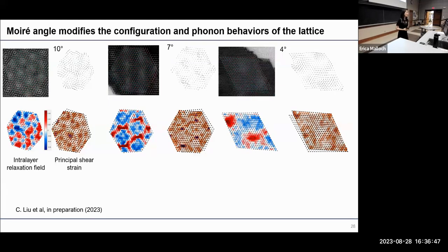We can actually map out the intralayer relaxation field together with the principal shear strain. Those features all arise because each layer is no longer a perfectly hexagonal lattice. Instead, they will be distorted in the presence of the other layer. We're currently on the lookout for moire phonons.